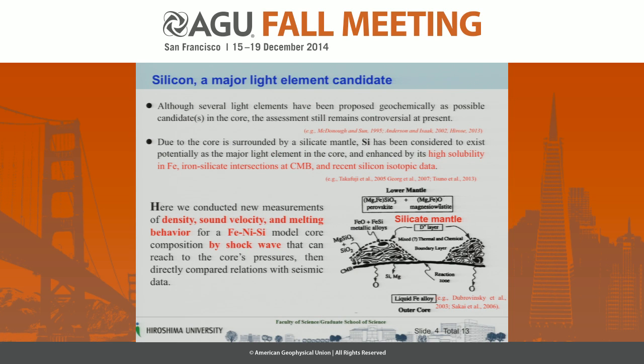Although several light elements have been proposed geochemically as possible candidates in the core, the assessment still remains controversial at present. Because the outer core is surrounded by the silicate mantle, silicon has long been considered a potential major light element in the outer core, supported by its high solubility in iron, iron-silicate interactions at the core-mantle boundary, and recent silicon isotopic data. Here, we conducted new experiments on density, sound velocity, and melting behavior for an iron-nickel-silicon model core composition by shock waves that can reach core pressures, and then directly compared our results with the observed seismic data.